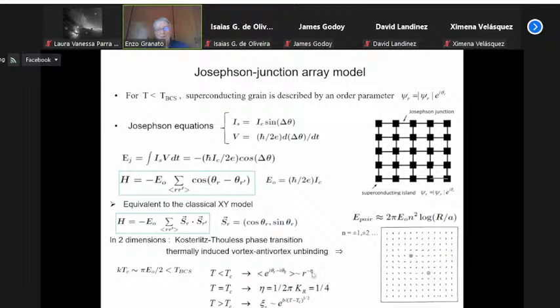And the power law exponent here depends on the temperature. But right at the critical temperature, it has a universal one. Above the critical temperature, it decays exponentially, and the correlation length has an exponential dependence on the temperature, diverging as T goes to T_c. But this behavior is quite different from the usual transitions, like a magnetic transition, in which the correlation length diverges as a power law.